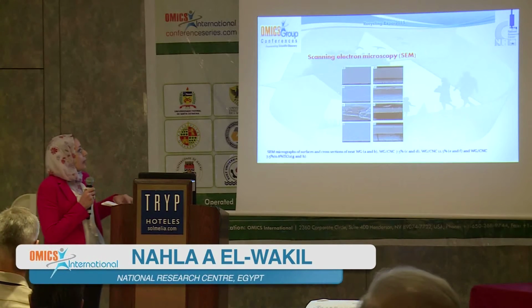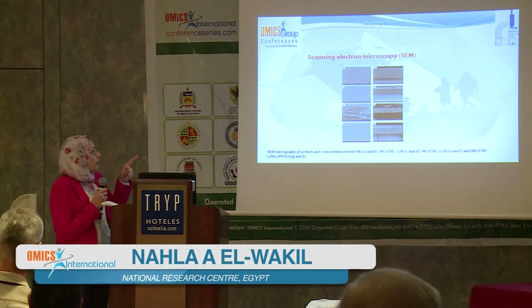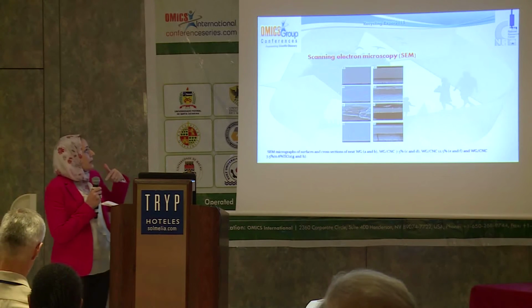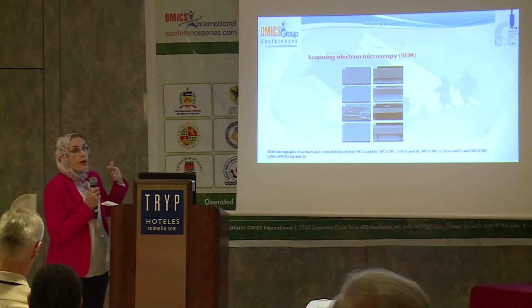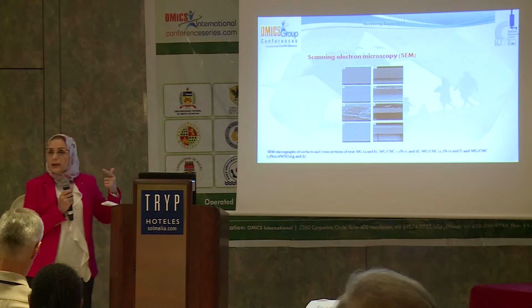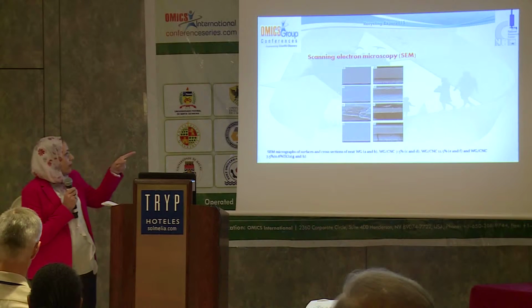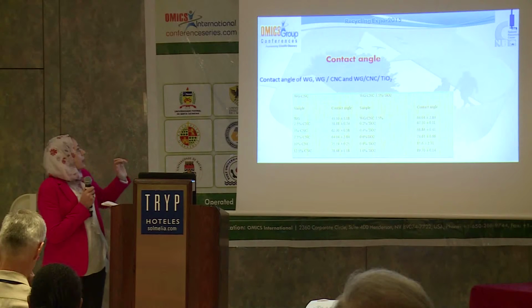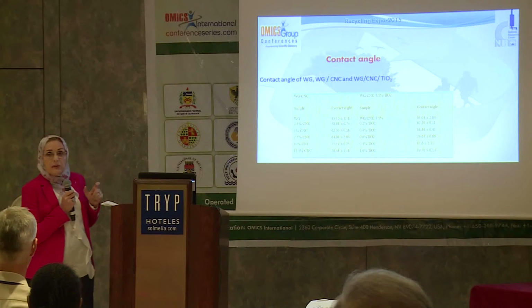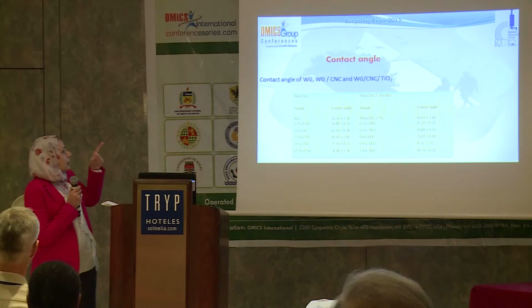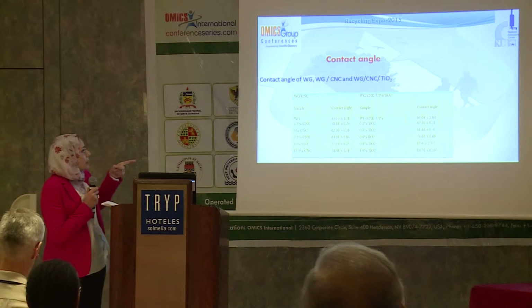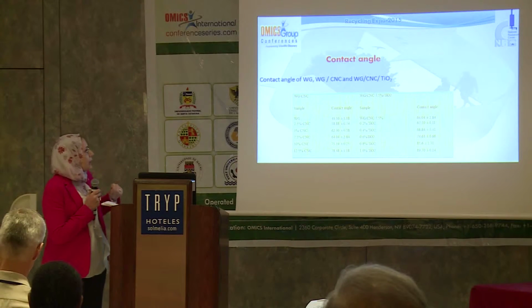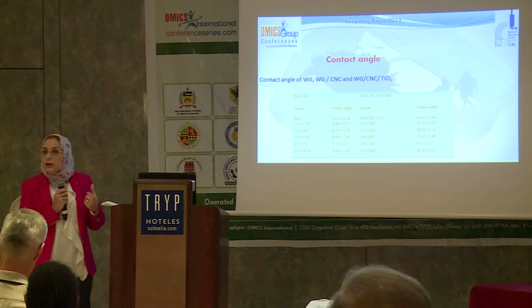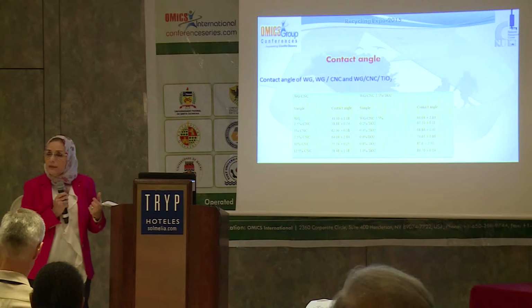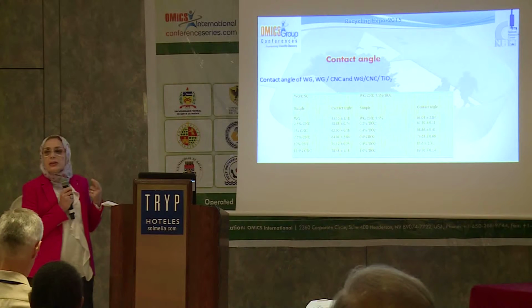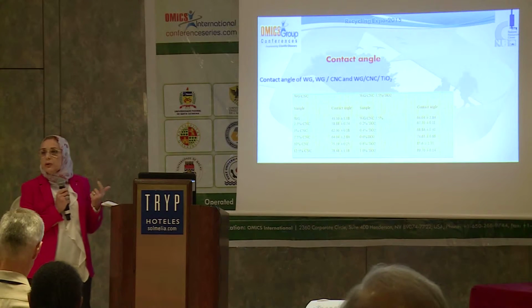The electron microscopy of the prepared films shows the homogeneity of the films, and filling the wheat gluten films with higher percentages of cellulose nanocrystals results in aggregation. The water sensitivity of the prepared films was characterized firstly by contact angle. We can see that filling the wheat gluten films with cellulose nanocrystals and titanium dioxide results in a more hydrophobic surface. Hydrophobicity of the films is a necessary character for films used for food packaging.